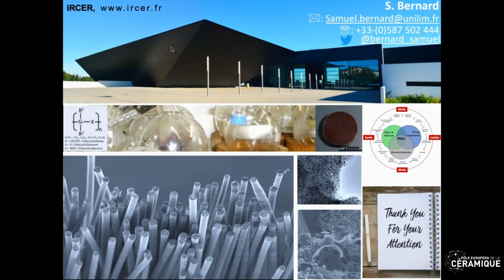Okay, thank you. Another question about thickness of the pieces. Can we imagine to build thick pieces of ceramic with PDC, and is the debinding an issue in this case? Okay, the thickness can be few millimeters, but we worked with CTTC in particular several months ago, and we were able to produce PDCs with a thickness of more than 50 millimeters, and the diameter was 100 millimeters. So it worked quite well, but you need to control the chemistry of your ceramic polymers and to use fillers inside. But you can produce ceramic pieces with a controlled thickness from few millimeters, 1 or 2 millimeters, as some example I showed previously, to several centimeters.